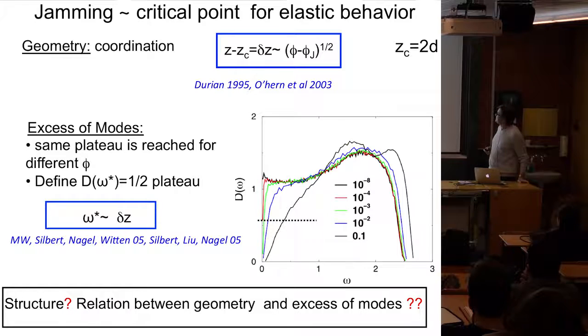The system here was, for example, a half-harmonic interaction potential. And then again, you heard about the fact that as you approach this point, those properties show scaling. You have scaling in the microscopic structure. For example, if you look at the coordination, it has a finite value at jamming, but then if you compress, it grows like the square root of the increased density. Here, this is just twice the spatial dimension.